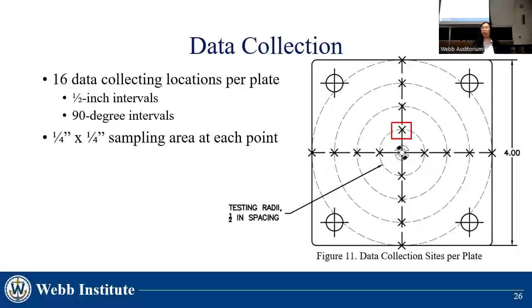Immediately following the retrieval of the primary trial plates, microbiology data was collected. At each X point, such as the one marked by the red box, a 1/4 by 1/4 inch area was scraped with a metal scalpel and then examined under the microscope at 40 times magnification. During the examination process, microscope footage was examined and images of microbiology growth on the plates were able to be observed at various data points. The various types, quantities, and locations of the growth were recorded.